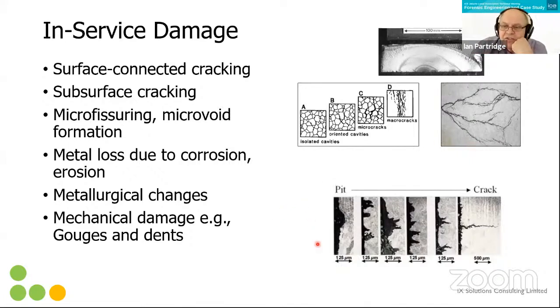The very bottom picture is interesting. I like showing this to young graduates and young engineers. All these types of defects, or damage, that's shown here are due to corrosion. So when people design things and put a corrosion allowance on, they're assuming something a bit like this. However, that type of damage is relatively rare. Most corrosion damage is more like these two. However, you can get some that are very, very sharp and act more like cracks till you get to a point where they are cracks. Now, these are created by corrosion. You don't think of corrosion generally as a cracking mechanism. And people do get confused, and these things do catch people out.